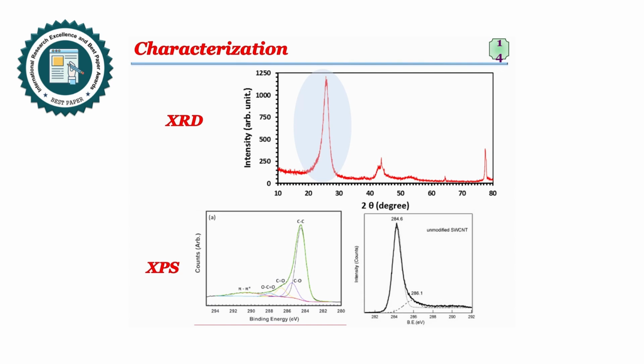XPS is also an important tool for the characterization of carbon nanomaterial. So here the C-C and C=O can be obtained from the deconvolution of C1s, and we can differentiate them from the deconvolution. Especially the sp2 hybridized or sp3 hybridized carbon can be obtained at 284.4 electron volts to 284.6 electron volts, and the dominant highly oriented C-C of unmodified single wall carbon nanotube exhibited sp2 hybridization around 284.6.